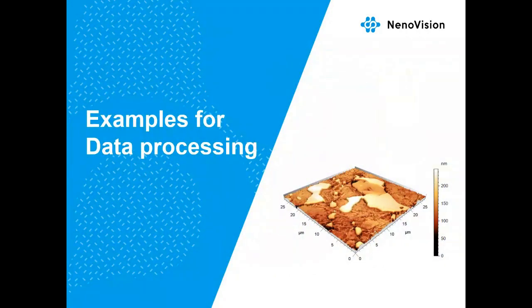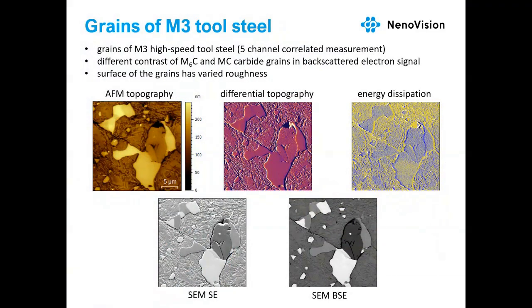Now I will shortly introduce examples which will then be shown in more detail during the talk of Arno. We selected two samples. The first of them is a grain of M3 high-speed steel. We simultaneously collected five channels, and you have the data, so you can check. You see the AFM topography. You see differential topography, also called the error signal. You see energy dissipation, which is equivalent to local elasticity. And then you see channels from secondary electron and backscattered electron data. Each of the channels looks a bit different, and we will show you how to analyze them using the software.